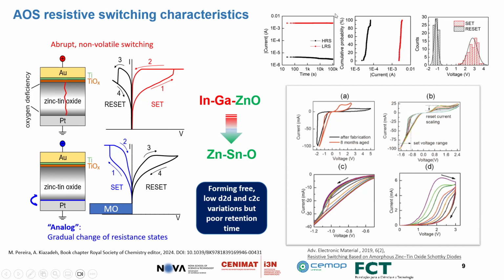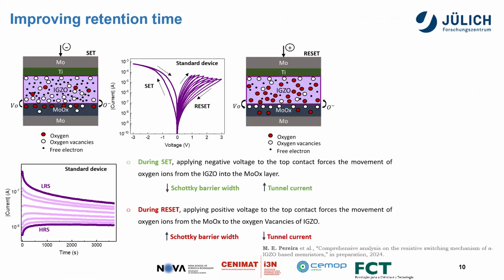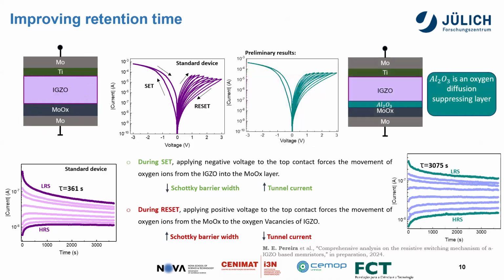The property on top that I am showing is more for the abrupt one with the non-volatile property, and then certain variation between cycle to cycle and device to device. So we have lots of advantages, but still a certain disadvantage for artificial neural network paradigms, like to train these devices and to keep the resistance states. In order to improve that, we need to know the mechanism. We believe it's a change of Schottky barrier profile that is happening during set and reset, giving more pronounced or less pronounced tunnel current during set and reset accordingly.